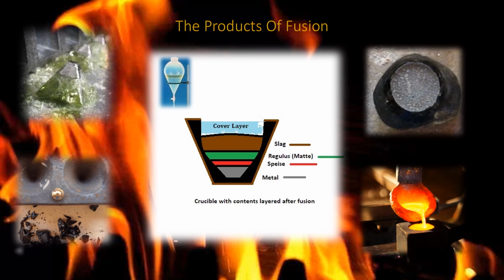If the slag is too acidic, it will be a thicker solution and stringy when poured. The last few drops from the crucible will form long strings or threads. If it's too basic, it will be lumpy as it's poured, and shots will break off during the pouring. When cooled and fully solidified, the appearance for a neutral or acidic slag should be glassy. A basic slag will have a dull and stony looking texture.